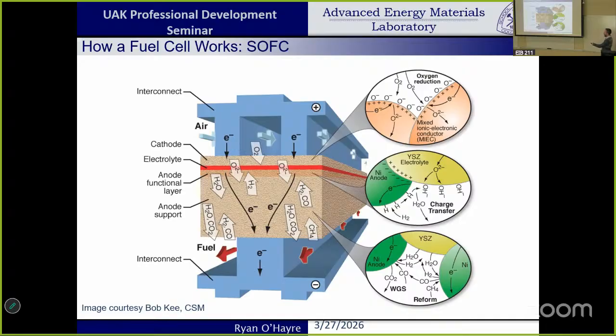The anode's also the one that needs to do all the fancy chemistry, especially if you're going to supply methane or coal or more complicated fuels, because those fuels have to be reformed. And you can do this internally in the pore spaces of the anode. So the fuel comes in and it gets reformed. And because this is nice and thick, we have plenty of residence time for all those fuel species to get reformed, so that by the time the fuel gets close to the electrolyte, it's mostly already decomposed into hydrogen. And so it's really the hydrogen then that reacts, just like it did in the other kind of fuel cell.